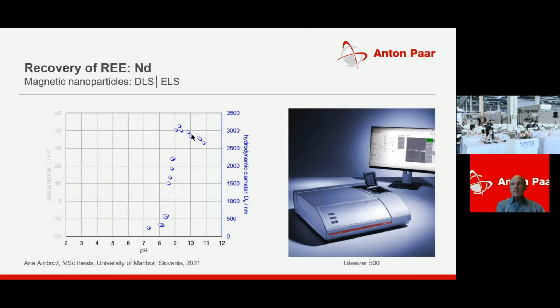We proceeded with the analysis of the pH dependence of particle size in order to cover different aqueous conditions for the neodymium ion adsorption process, which depends on the feed solution, such as a wastewater solution. When we move to higher pH, we observe a sudden increase in the hydrodynamic diameter, showing some kind of peak at 3 micrometers, which occurs around pH 9.